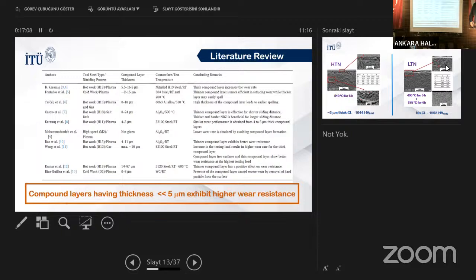Those are the authors, the type of the tool steel, the thickness of the compound layer, and they have run conventional sliding tests, not impact-sliding tests. Those are their testing conditions and their findings. What we finally concluded is that the thickness of the compound layer should be much lower than 5 microns. From this point of view, we noticed that the thickness of the die material the company was using was thicker than 5 micrometers, but it should be less than 5 micrometers.